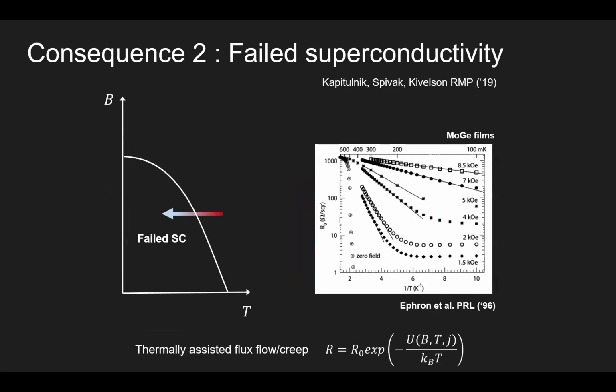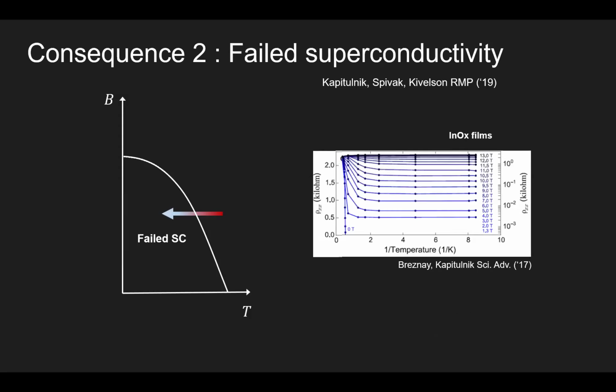Also, interestingly, you may have heard there will be a discussion this afternoon about failed superconductivity, which is when some people have seen that if you cool down in the mixed phase a 2D superconductor or thin films, the transition fails and you end up with a saturated resistance. This is an example of indium oxide.